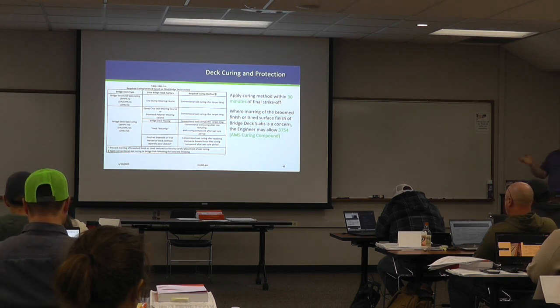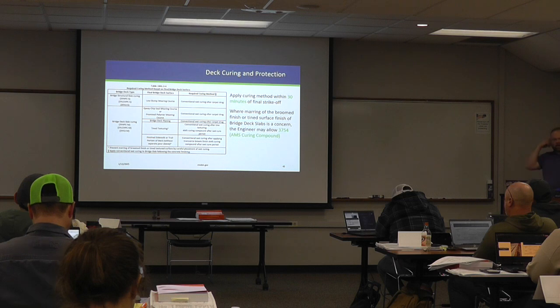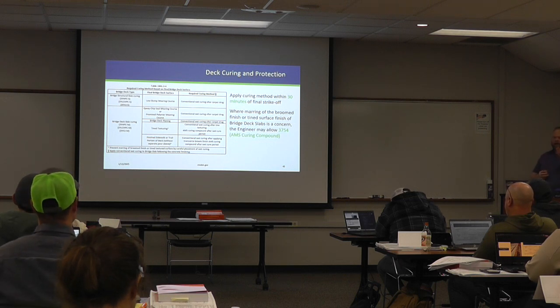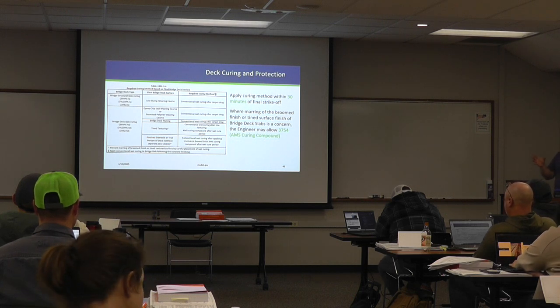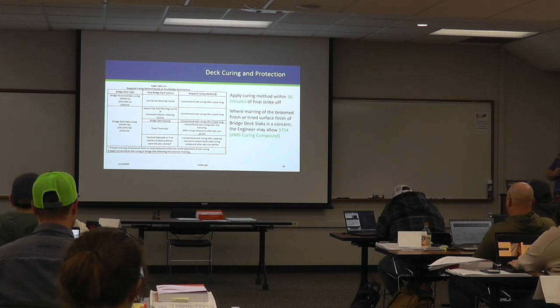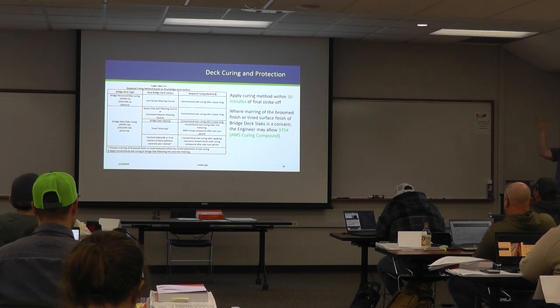Now they both work well for curing, but the difference between a wet cure and curing compound is that the curing compound, if it's placed properly, will trap all of the mixed water in the surface and cure the concrete. The advantage that the wet cure gives is that you provide a moisture source for the concrete if it needs it. So it might seem counterintuitive, where we don't want to work water into the surface. Well, that's us doing something to the concrete, whereas if we put wet curing down, the concrete has a moisture source here that it could use, and it's going to pull the moisture out itself. So you're not doing anything extra to it.